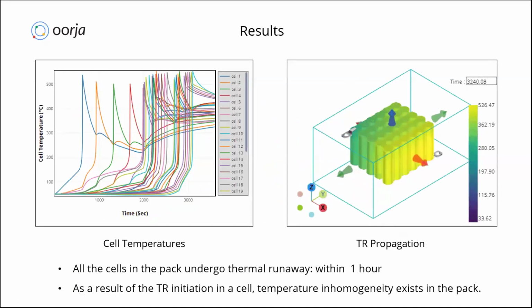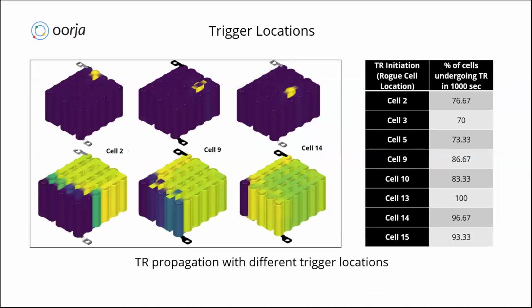Now, in order to avoid this thermal runaway propagation, the modifications that we have done, I will just discuss in the next slide. I forgot to mention that we also studied that rather than having this corner cell as a trigger cell, if we consider different cell locations as the defective cells, how the thermal runaway response of the pack looks like. And as you can see over here, based upon which cell has been triggered, you can see the percentage of cells going into thermal runaway. Obviously, cell 13 is somewhere around the center, and whenever the center cell goes into thermal runaway, the total number of cells undergoing thermal runaway is 100%. That is, the entire pack went into thermal runaway.